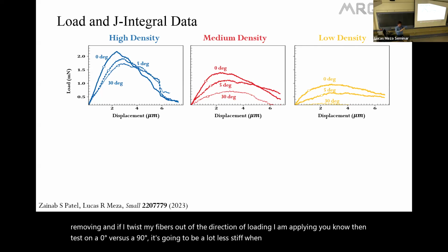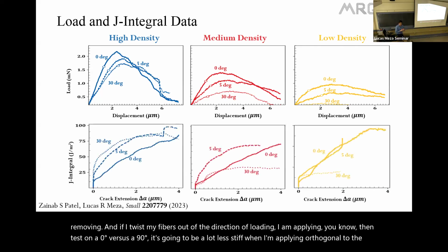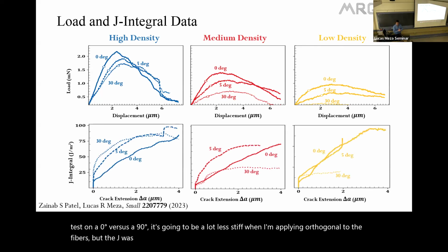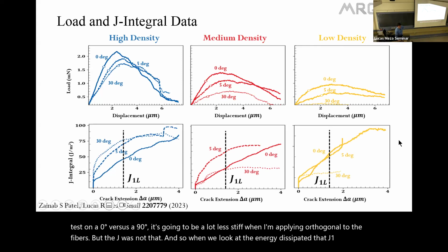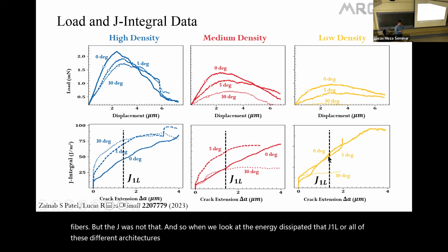And if I twist my fibers out of the direction of loading, if I am applying a bend test on a 0 degree versus a 90 degree, it's going to be a lot less stiff when I'm applying a load orthogonal to the fibers. But the J was not that. And so when we look at the energy dissipated, that J1L, for all of these different architectures, there's actually not a drop off at all. So the toughness here was not following this rule of mixtures.